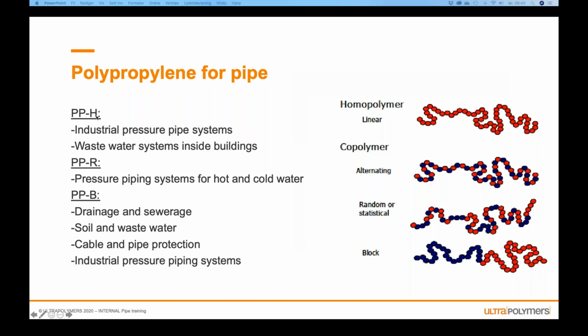Because homopolymer of polypropylene has a very low impact strength. In Norway, we can have areas where in the winter is -30 degrees, and if you are installing something underground at -30 and using a homopolymer, it will crack, definitely.